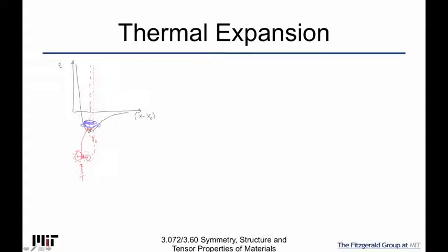So you can just see, just in this curve, that if I'm going to sample higher and higher points on this energy curve, and there are states that can be higher up here, the mean distance between atoms is going to increase because this is flatter on this side. And if I average over here, and there are more and more points way out here, you can see it going up, but it's not going up that fast. Way over here, I've got all these points I'm averaging over. You could tell that the hotter it gets, the more this average bond distance is going to go to the right. So how do we do that mathematically?